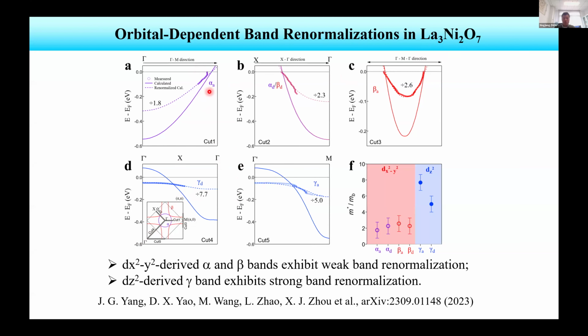In this case, we have measured the alpha band along the axis, and compared with the calculated band, this is something like a 1.8 renormalization factor if we want to make them match each other. Also, this is the alpha beta bands along the diagonal, calculated one and measured one. This is the beta band, measured and calculated. This is about a 2.6 renormalization factor.